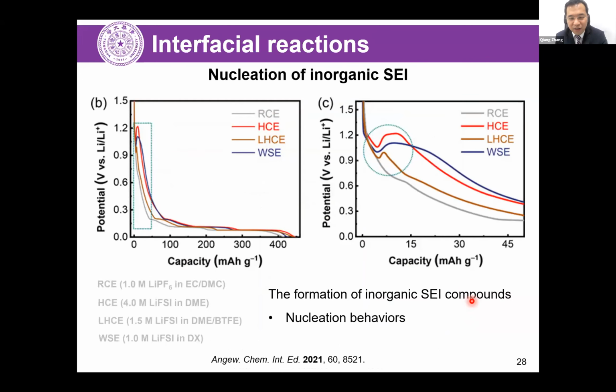And we also try to probe, if we change the electrolyte structure, then what happens? For example, in routine carbonate electrolytes, the capacity versus potential showed quite rapid decay. Well, for the case of high concentration electrolytes, it is found there is a small peak at the beginning, then the platform. Well, for the case of localized high concentration carbonate electrolyte, in which we try to introduce some solvents that don't dissolve salts, but can mix with another solvent easily, in this case the peak reduced a bit, but there's still a peak before the platform comes.